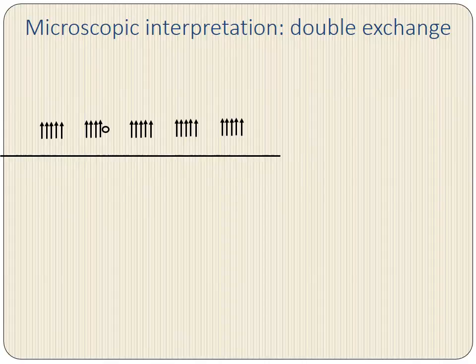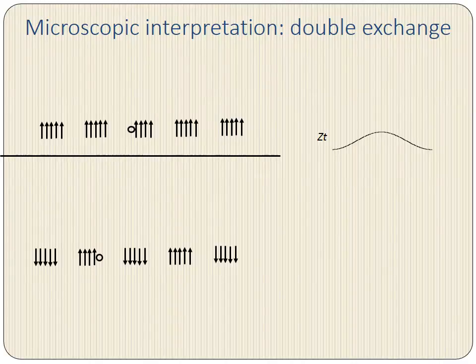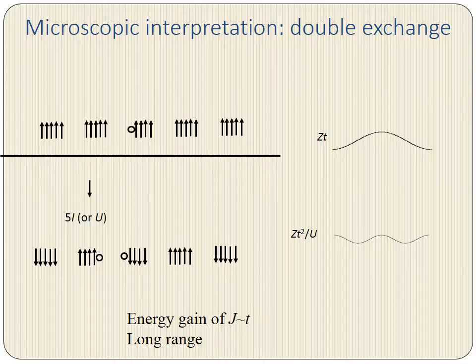For a ferromagnetic alignment, a hole can hop from one site to another rather easily and achieve delocalization. This will give rise to a 1-electron band that has width of the order Z times T, where Z is the coordination number of the manganese site. For an antiferromagnetic alignment, for holes to propagate, one of our electrons needs to be promoted to an unoccupied state, which, as we recall, is Hubbard split by energy U. This will lead to a 1-electron band with bandwidth of the order Z times T squared over U. So what we see here is that in our double exchange description, there is an energy gain on the order of T when the magnetic configuration is ferromagnetic. We can also see that this gives rise to a long-range interaction.